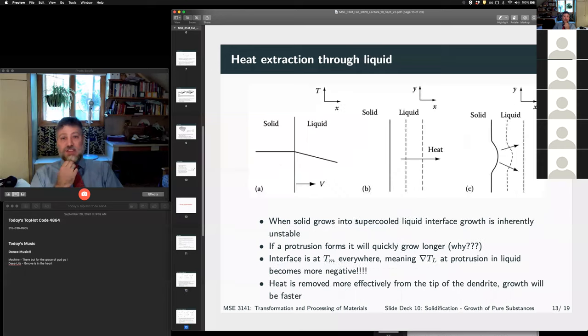The opposite is true if we're extracting heat through the liquid, right? So that means here we have a supercooled liquid and we've nucleated either homogeneously or heterogeneously on the solid, right? But now think about what happens if we have a bump, right? We still have essentially a shallower gradient in the solid, but we have a steeper gradient in the liquid.